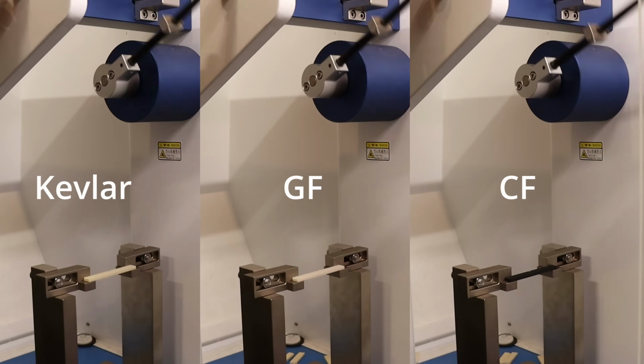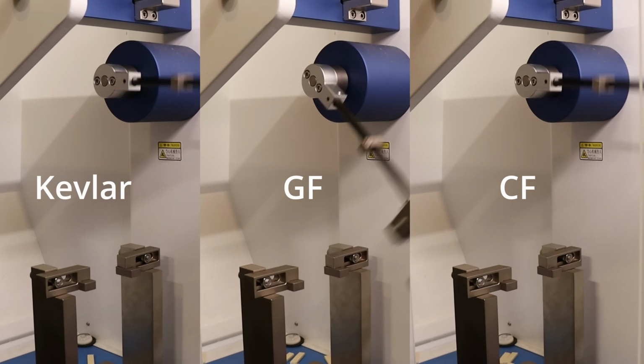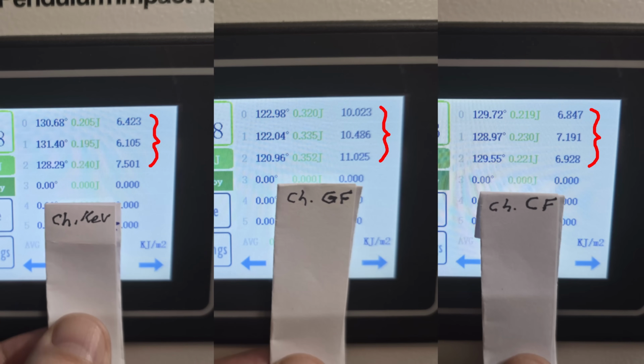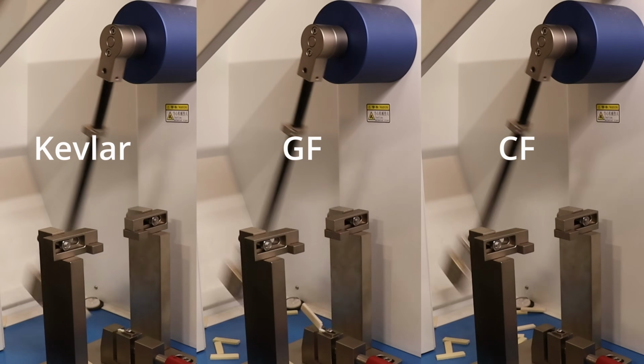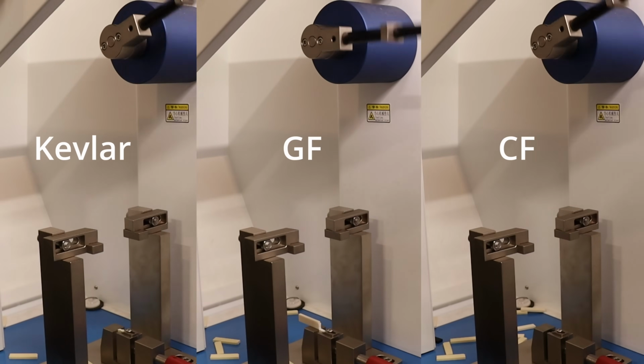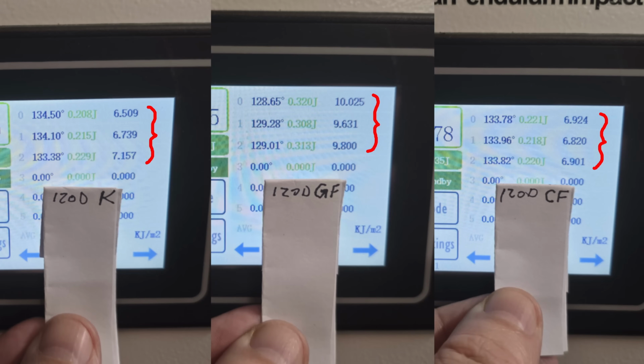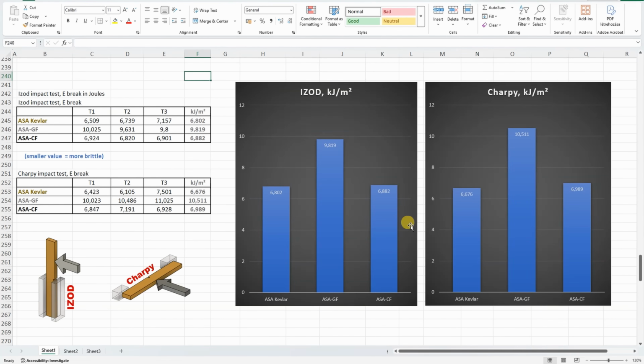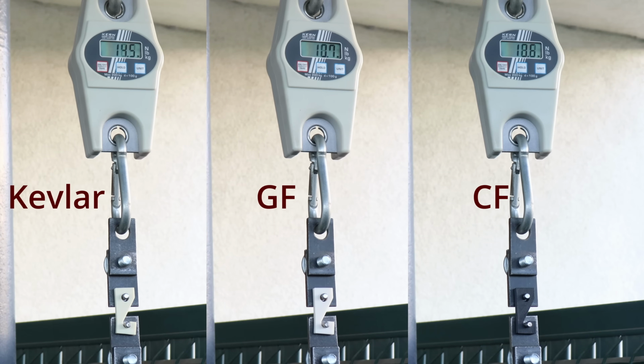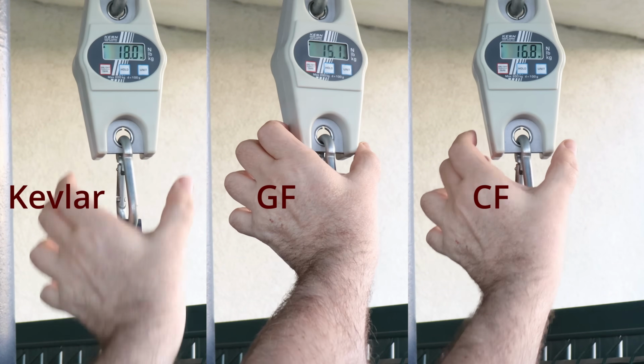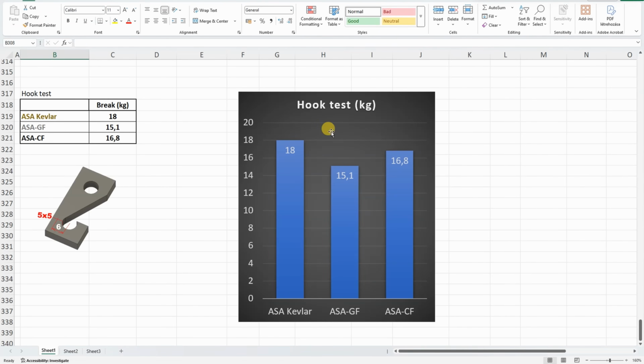Impact test, Charpy standard. And the results from 3 measurings. ISO impact test. And again the results from 3 measurings. Looks like the Kevlar and the carbon fiber version have a very similar brittleness, and the toughest between these 3 is the glass fiber version. A simple hook test. The strength here is very similar and actually quite weak compared to other material types, because weak layer adhesion will also result in weak wall adhesion, and this is important in this test.